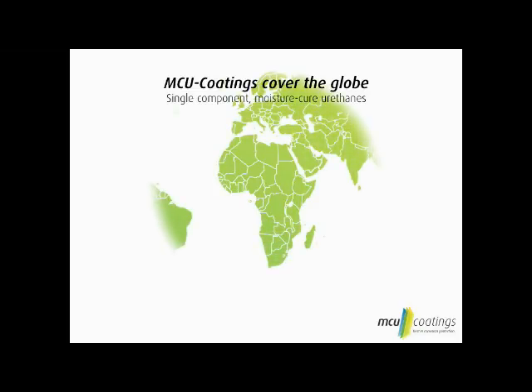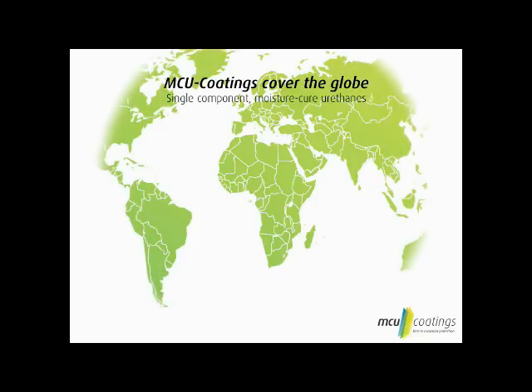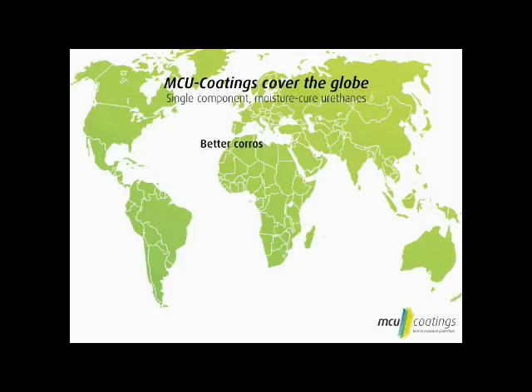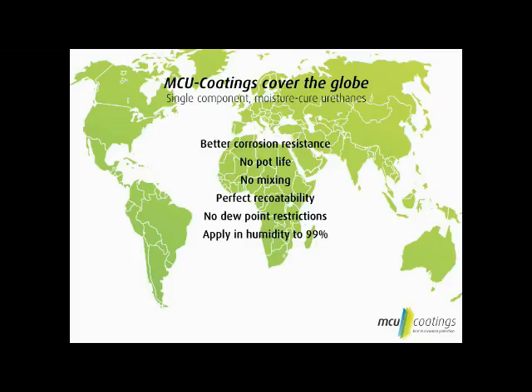These single-component moisture-cure urethane coatings have superior performance worldwide, not only in temperate climates, but in extreme environments with temperatures as low as -12 degrees centigrade and humidity as high as 99%. Further, these coatings offer better corrosion resistance, no pot life, no mixing, perfect recoatability, no dew point restrictions, the ability to be applied in humidities to 99% and temperatures as low as -12 degrees centigrade. Longer coating life. Faster cure time. In short, these coatings will solve your coating problems. Get the MCU advantage today.